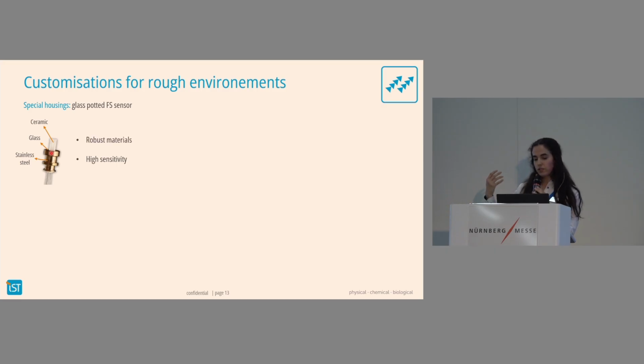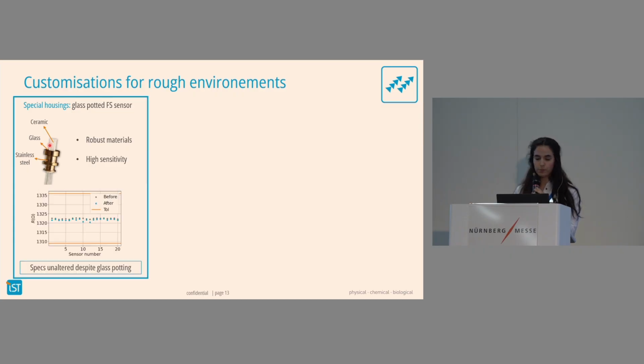And what is interesting is that these are all very thin and very robust materials, and we don't compromise the sensitivity because nothing comes on top of the sensor. And what is more important is that the resistance of the sensor before this housing process and after this housing process is unaltered, meaning that it's unaffected by this.